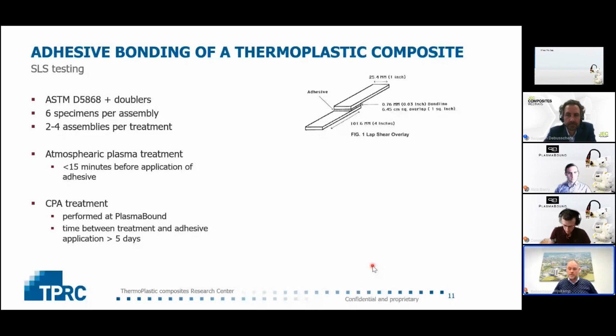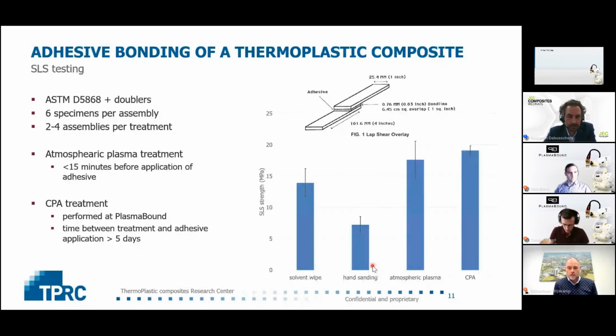These are the results. Funnily enough, with this material combination of the epoxy film adhesive and low melt PEEK, we already achieve a single lap shear strength of about 15 megapascals just using a solvent wipe. If you look at hand sanding, which would roughen up the surface and maybe activate the surface, it resulted in a lower shear strength. So probably we have contaminated the surface of the thermoplastic material. And then we saw that with both plasma treatments, atmospheric with the plasma pen and the CPA treatment, we were able to increase the lap shear strength to 20 megapascals.